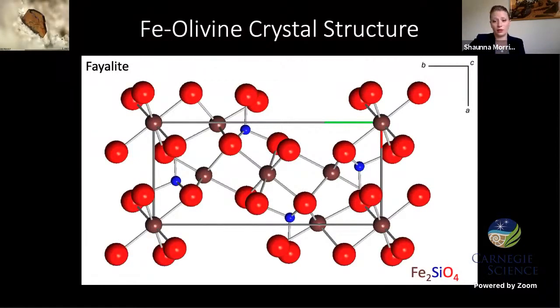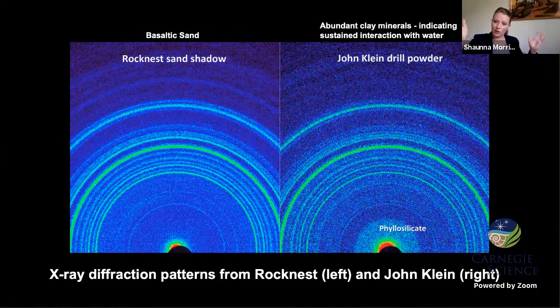What's really nice about this technique is that we can do this for all of the mineral phases that we found in Gale Crater, not just olivine. And furthermore, the CheMin instrument was not originally intended to do this. So after the launch, we were actually able to use this technique and these principles to essentially retrofit or calibrate CheMin to have a much higher precision than originally planned. And as a result, we've been able to gain a lot more insight about the real composition of minerals on Mars. So what minerals are we finding on Mars other than olivine and gypsum? Here are the two-dimensional X-ray diffraction patterns of the first samples we analyzed with CheMin in Gale Crater. The first, Rocknest, was a scooped soil.